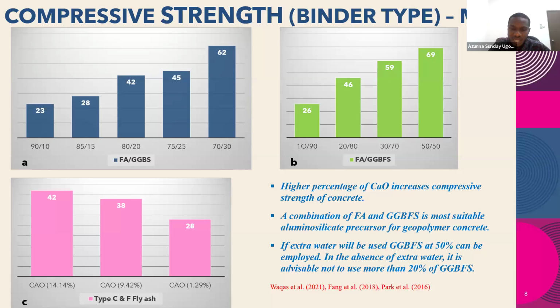talking about the binder type, you can see that the strength for the first mix increases when you increase the GGBS content in it. So what it means is you need to have a balance of silicon oxide in your binder and calcium oxide also. So where we have 90% fly ash and 10% GGBS, you can see the strength is just about 23 MPa. And as you increase the content of your calcium oxide, your strength begins to go up because the percentage of calcium oxide in the binder is coming up.